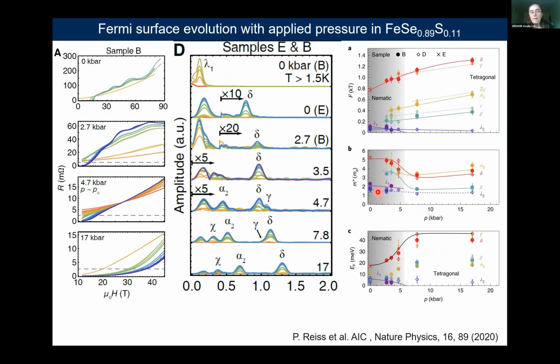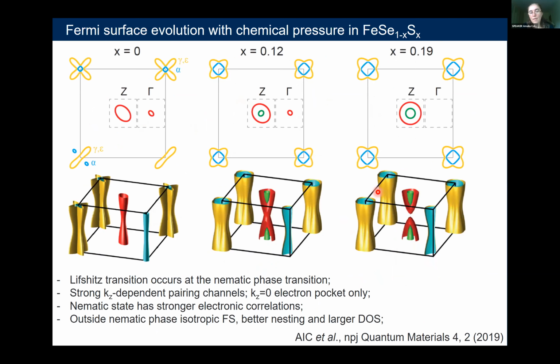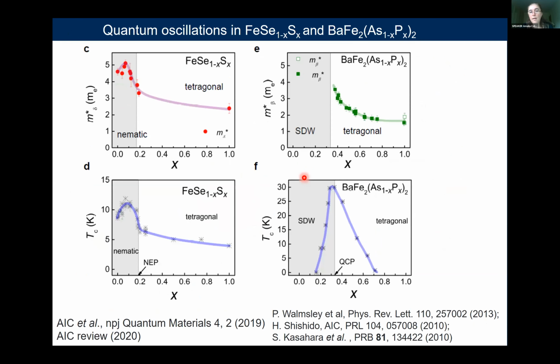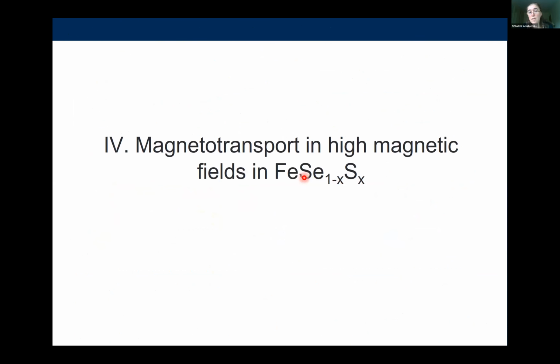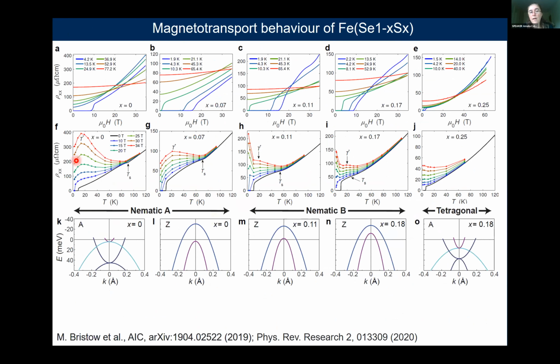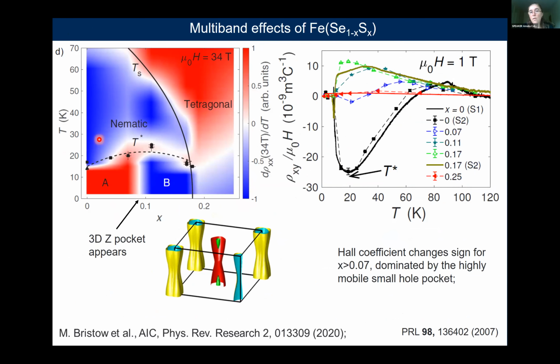For a system like the iron selenium sulfur system, these are multiband systems. The physics of a multiband system is dominated by small pockets with high mobilities. What we know is that, for example, this hole carrier here has a very light mass. Also from ARPES, we know that this has much higher velocities, so that means it's going to dominate the transport. We can see how it affects this in particular in magnetotransport. For example, you see very large magnetoresistance at very low temperature, but also in the Hall coefficient. And the Hall component in the magnetic field is very unusual.